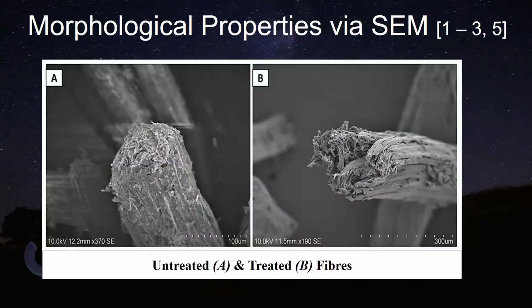And after the chemical analysis, we did the morphological analysis, and that's even clearer to you. You can see on the left-hand side, that's the untreated fiber, and on the right-hand side, that's the treated fiber. After the treatment, all those pectin, debris, and wax have been taken out, and that's why the fiber surface becomes rougher, and that rougher surface is good for enhancing the adhesion property. And when hemicellulose has been taken out, we are left with only cellulose and lignin, and those are actually contributing to thermal and mechanical properties.